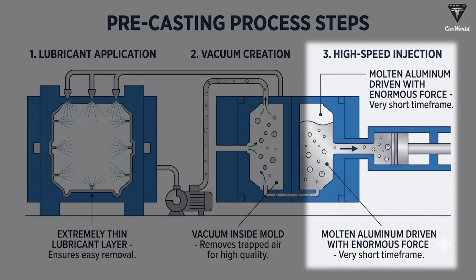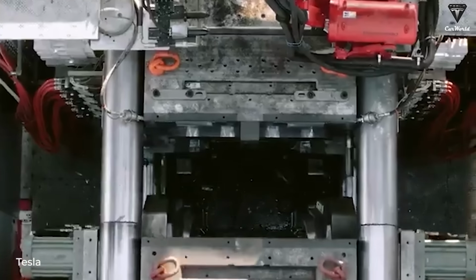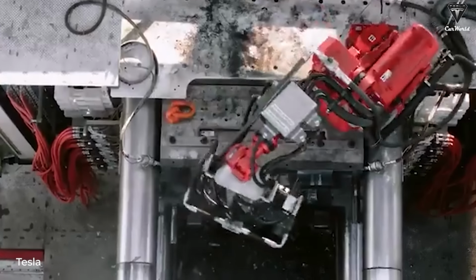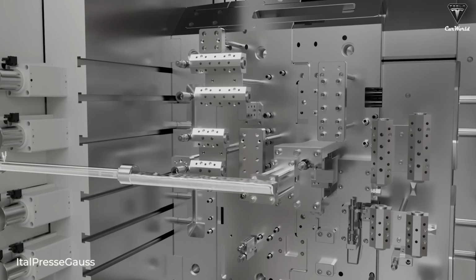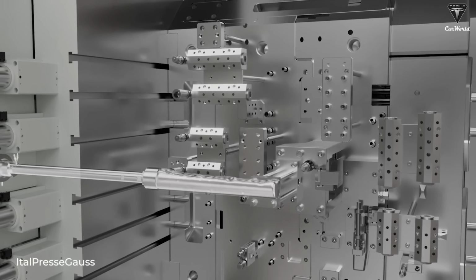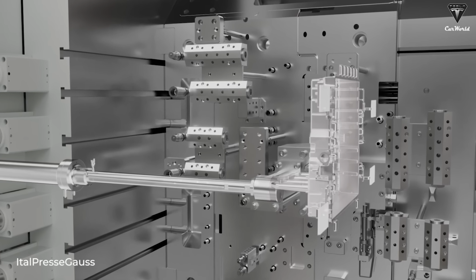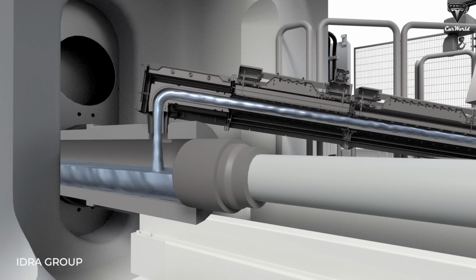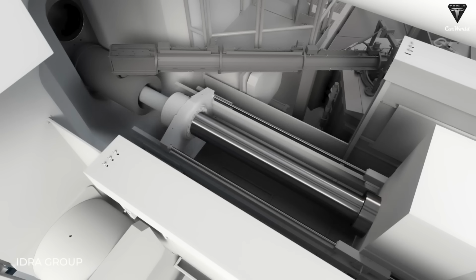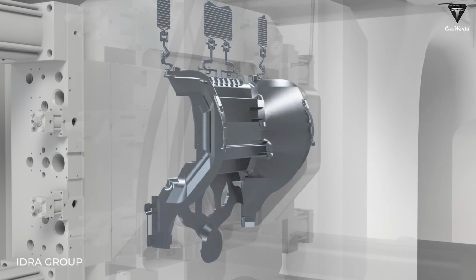Once everything is ready, a high-speed piston drives the molten aluminum into the mold cavity with enormous force. And from that moment on, everything happens in an incredibly short amount of time. The hardest part is being fast without sacrificing precision. If the metal is injected too quickly, trapped air or flow-related defects can compromise the internal structure. But if it's injected too slowly, the aluminum can begin to cool before the entire mold is filled.